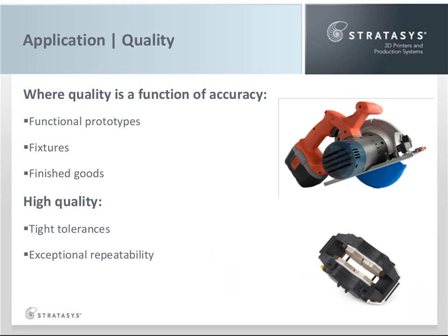For functional prototypes, fixtures, and finished goods, accuracy takes precedence, and that is paired with repeatability when you need more than one. For commercial or industry parts that are routinely injection molded, thermoformed, investment cast, or die cast, for example, product designs tend to avoid tiny features and paper-thin walls. So in this case, an additive manufacturing technology that replicates features larger than 20 thousandths of an inch will get the job done, as long as it manufactures all those features to the same stringent standards, namely tolerance and repeatability, as the traditional manufacturing process. And those stringent standards are never expressed in dots per inch.